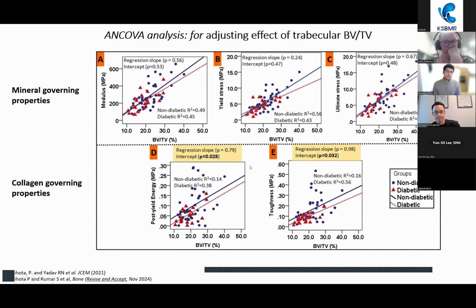And then we ran ANCOVA analysis only for trabecular bone, because our mechanical properties were correlated with bone volume fraction. And we wanted to make sure whether reduced mechanical properties are because of the effect of glycation or because of low BV by TV. And when we adjusted the effect of BV by TV from mechanical property, we found that mineral governing properties are no more significant in the diabetes group, whereas the collagen governing properties, post-yield energy and toughness, are lower in the diabetes group. So it confirms that the degradation in the post-yield property is not because of the low BV by TV, whereas it is because of the increased glycation.